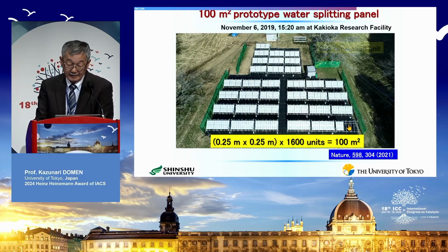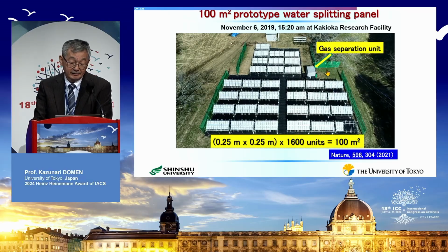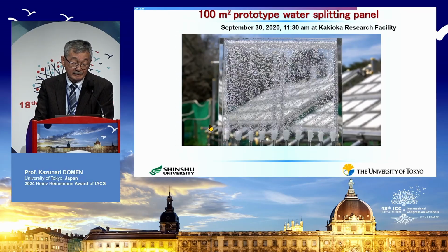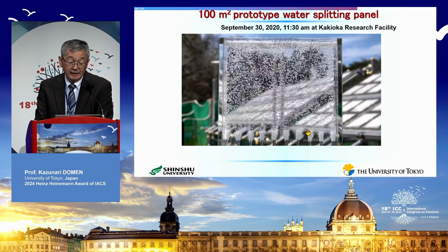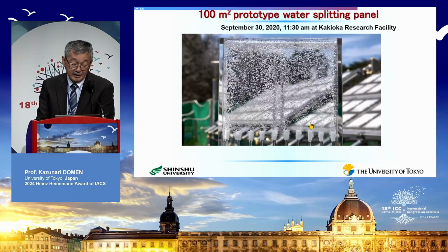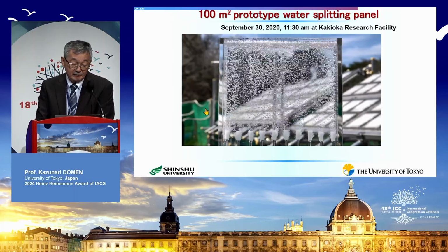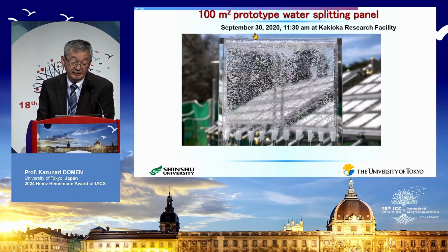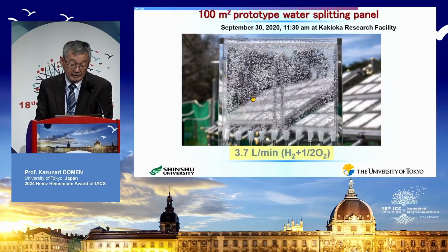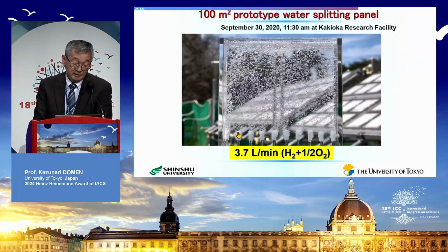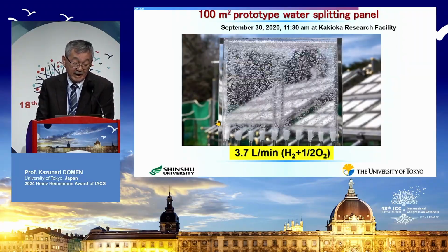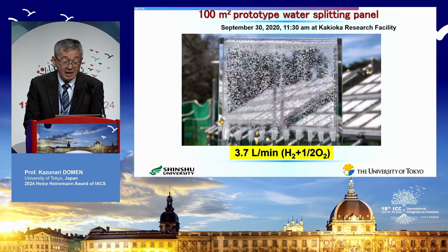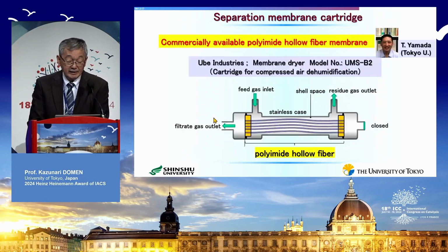In addition to that, this is a gas separation unit. And these are the bubbles of hydrogen and oxygen evolving before introducing into our gas separation unit. This experiment was carried out September 30th, in the beginning of fall, so at this stage we obtained about 3.7 liters per minute of hydrogen and oxygen evolution. Then we separate hydrogen from this mixture.